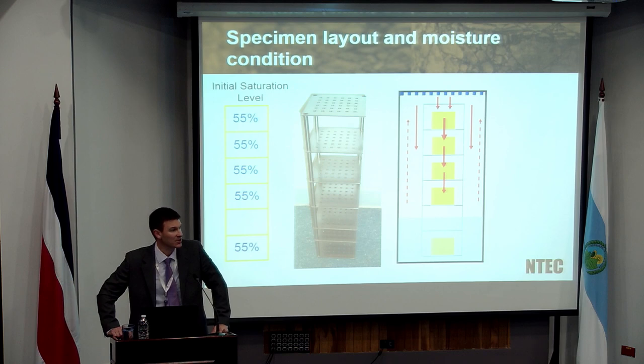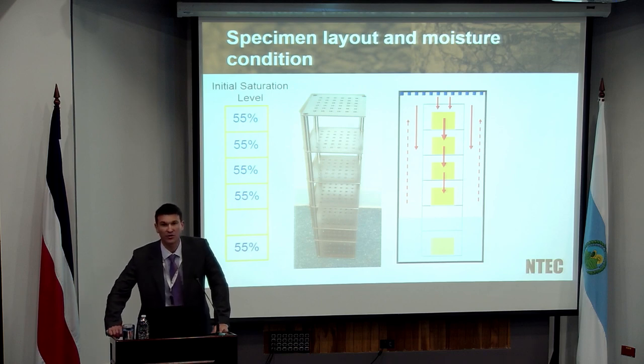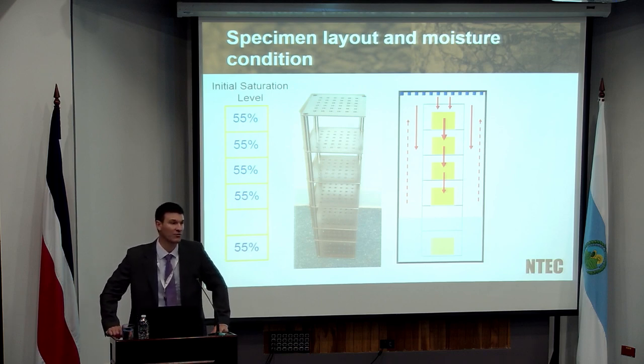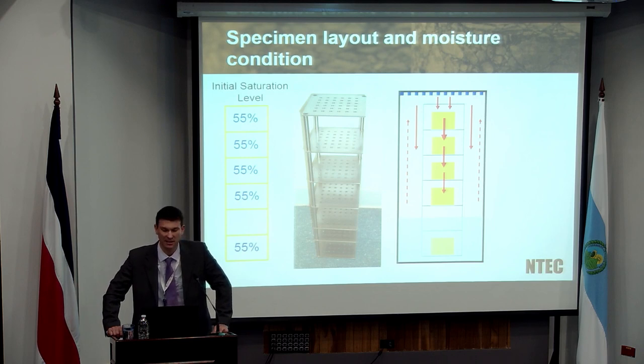We would initially saturate them. So you do exactly the same kind of protocol that you would if you were doing the AASHTO T283. You do some kind of vacuum saturation. And on the left-hand side, I've given you examples. We would get roughly the same saturation. It will vary, but let's assume we've managed to produce 5 specimens with roughly 55% saturation level.